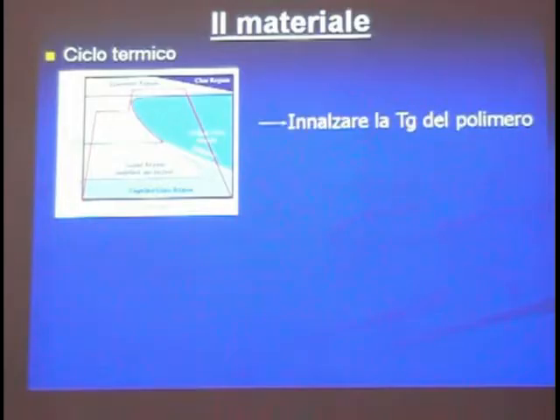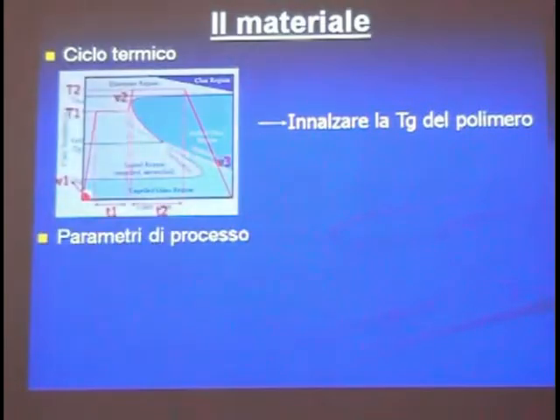This is a so-called TTT diagram, temperature time transformation diagram. You may see that the red line shows the curing cycle, which is composed of two steps, one at an intermediate temperature and one at a high temperature, in order to reach the gel glass region and so get correct properties out from the matrix. The basic scope is to get a glass transition temperature as high as possible from the polymer.